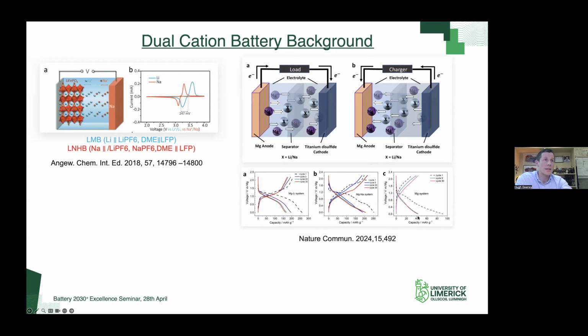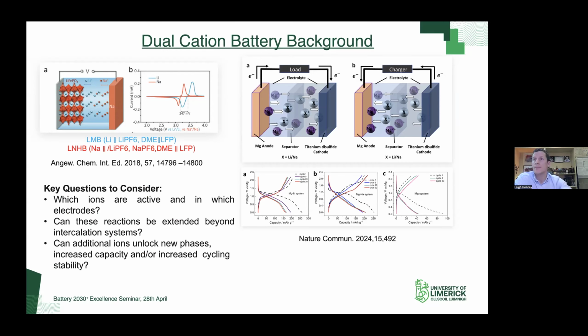volts versus magnesium. If we then pay attention to the capacity, you can see in the magnesium system down here that the reversible capacity is around 40 milliamp hours per gram. Whereas with the dual systems, magnesium and sodium and magnesium and lithium, it was more around 200 milliamp hours per gram. Essentially they were getting additional charge storage mechanisms, which for us was a really exciting background idea that we wanted to try and bring into our work.